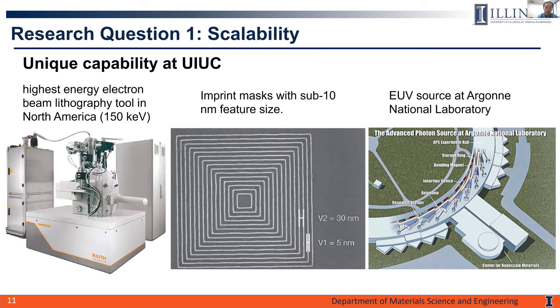So to answer this question, we will define the phase masks using the 150 keV e-beam lithography system we just acquired here at UIUC, and also using the EUV light generated at the Advanced Photon Source at the nearby Argonne National Lab to expose the HSQ-based photoresist. After exposure, we form the 3D nanostructures, and the film's dielectric and mechanical properties will be fully characterized. So the target is to establish the technological feasibility of forming the perfectly ordered porous dielectric by proximity field nanopatterning as the next generation low-k dielectrics for microelectronic applications.